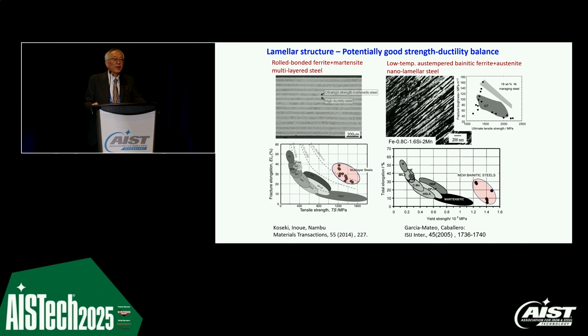I think the lamellar structure itself is also very interesting in terms of a better strength and ductility balance. This is one big project in Japan, a laminated structure. Martensite is covered by soft iron. And actually, when we compare with the banana curve, they succeeded. Professor Koseki at Tokyo University and colleagues succeeded in getting a better strength and toughness balance.